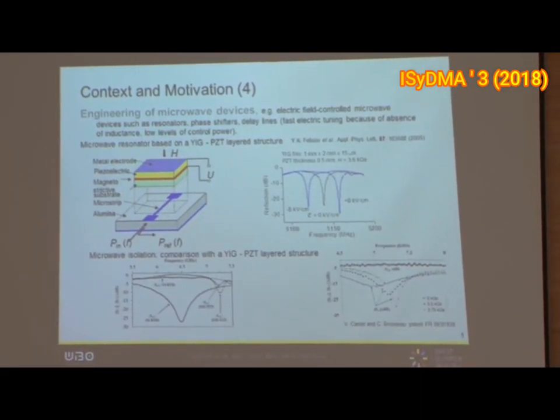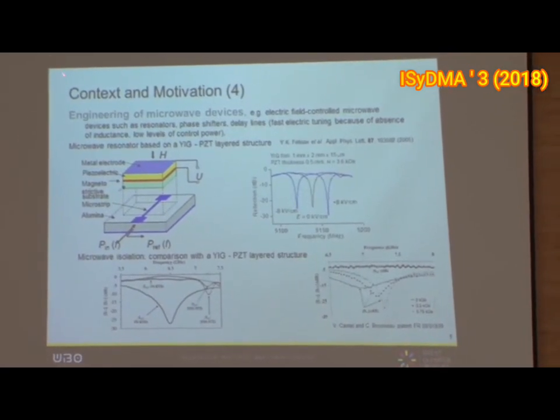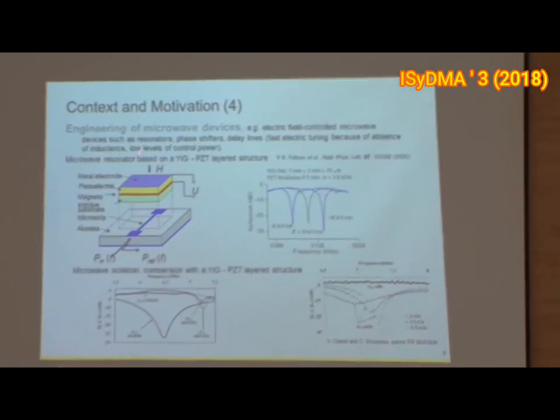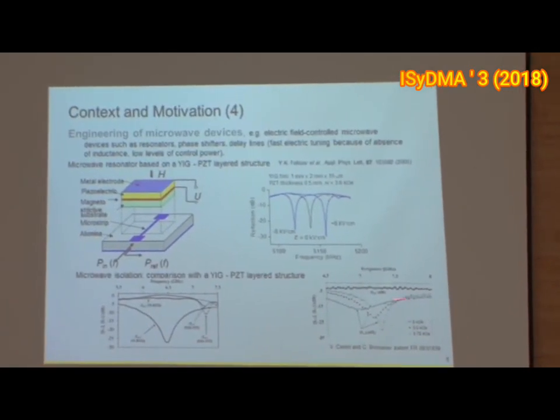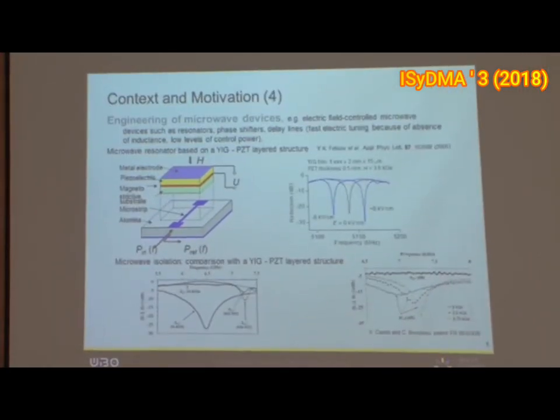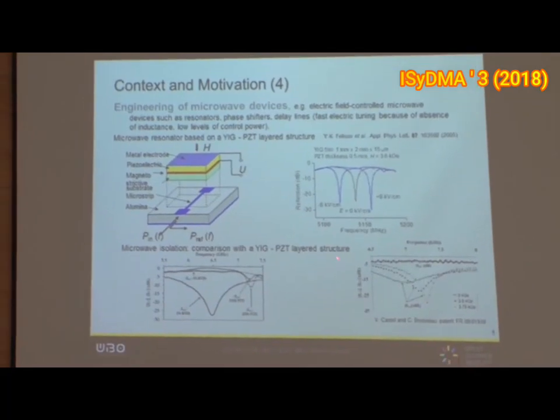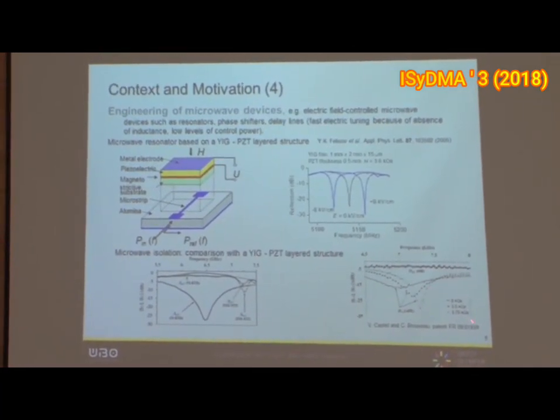So what we did is, using a material, nickel and barium titanate, we exactly duplicate the system, but not with electric field excitation, but with magnetic field excitation. And we exactly observed the shift depending on the magnetic field excitation.